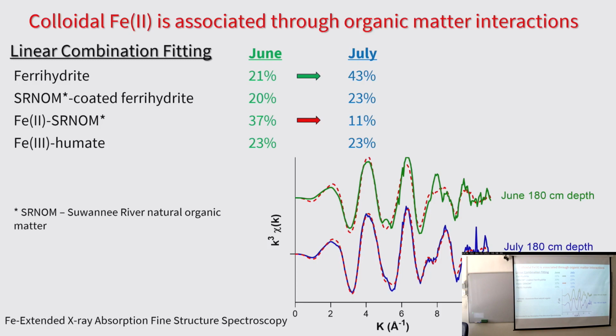Now that first of all validates all the previous results that I have shown you, that ferrihydrite is a significant contributor to the colloidal assemblage, and also that we have a contribution of organic matter interactions. It also shows that the iron 2 is most likely present due to organic matter interactions. Now, comparing between June and July, we can see that there is a lower contribution of ferrihydrite in June, and that the iron 2 organic matter interactions are nearly 40% of the total iron within the June sample.